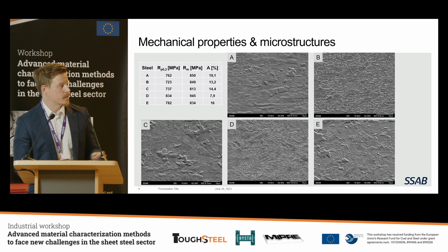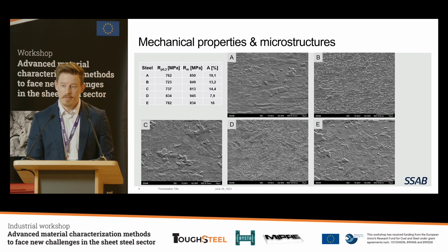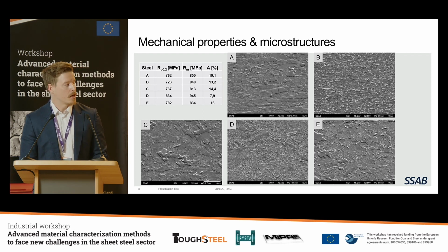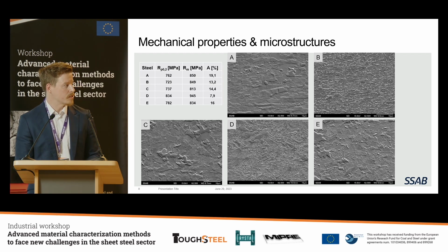You can see that steel A is quite a pure ferrite, polygonal ferrite. Then we have also really complex phase steel as a B. Including, let's say, bainitic ferrite and MA islands. And then C is again based on a ferritic microstructure, not so polygonal anymore, maybe a little bit more quasi-polygonal ferrite there. Then D is, let's say, mix of all salads.